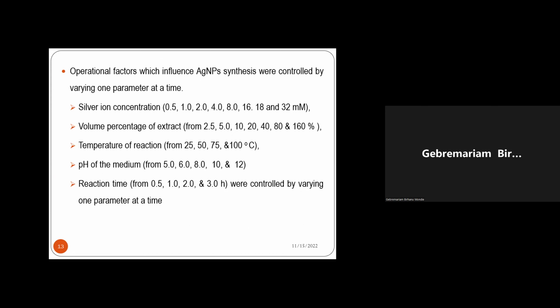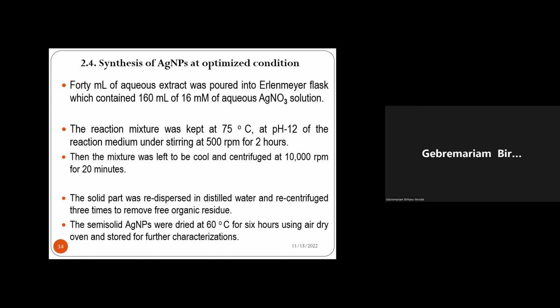So these are some of the operational parameters that affect the biosynthesis of silver nanoparticles, which were optimized: the concentration of silver salts, volume percentage of the plant extract, temperature of the reaction, pH of the media, and reaction time. These were the main parameters optimized for maximum yield of silver nanoparticles using the green synthesis method. The optimization was conducted by controlling the other parameters and varying one parameter at a time.